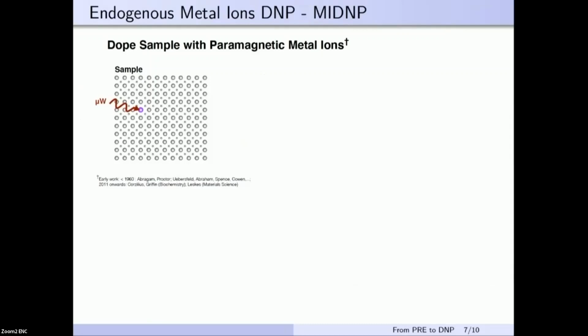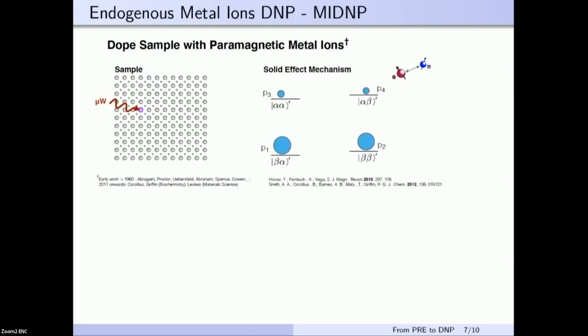So the first question that we asked ourselves is, how far can we polarize in the sample, from one electron inside into the bulk of the sample? And to answer that, we have to look at the relevant DNP mechanism. In our case, it's almost always the solid effect. The solid effect we can describe with a two-spin system of one electron coupled to one nucleus.